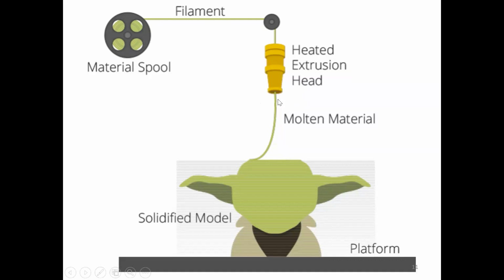and based on the nozzle size. Typically the nozzles come with a 0.4 millimeter or 400 micron aperture, through which the filament will be melted and fed. Why I mention this nozzle diameter is, please do remember, as I said, the minimum clearance in the system decides the aspect ratio or the diameter of the reinforcement, the diameter of a short fiber or a long fiber or a particle and so on. So if it is 400 microns, you know the thumb rule: the particle or the diameter of the reinforcement should be 1/10 of that. So this is where we always need to have a check.